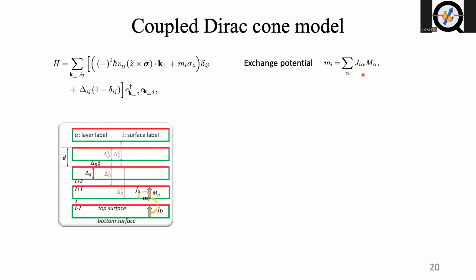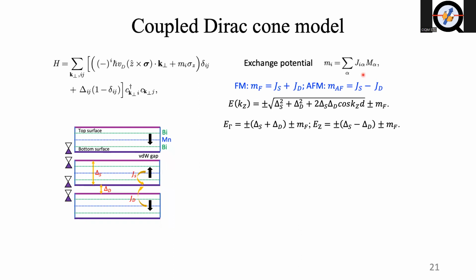Delta IJ denotes the coupling of the I Dirac cone with the Dirac cone on the J layer. Let's simplify our model by only considering the important parameters, which are delta S, delta D, JS and JD. Sorry, I forgot to introduce JS and JD. They are the exchange coupling between the Dirac cone and the magnetization. JS means the same layer, and JD means the adjacent layer. If we reduce this Dirac model to only consider delta S, delta D, JS and JD, we can simplify the model as such. We get rid of those high order coupling or hopping terms. In this case, the exchange potential M in the ferromagnetic case can be written as JS plus JD.